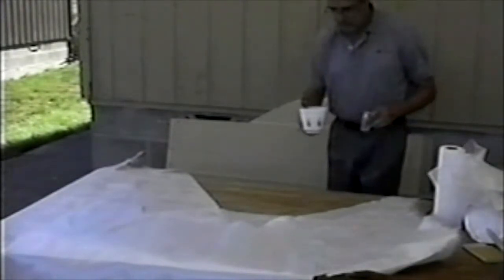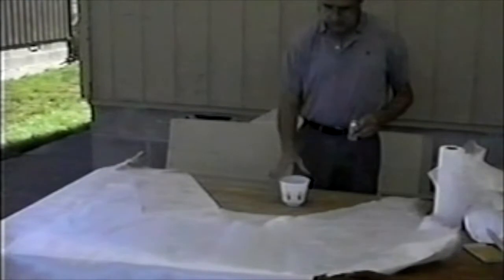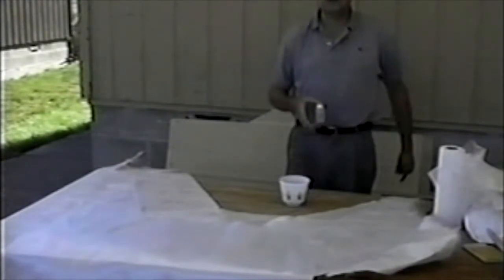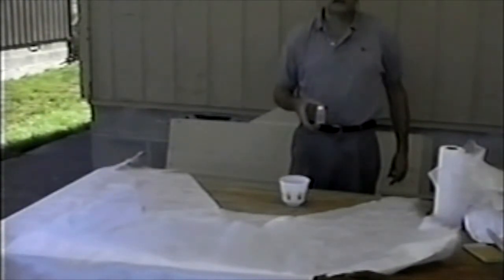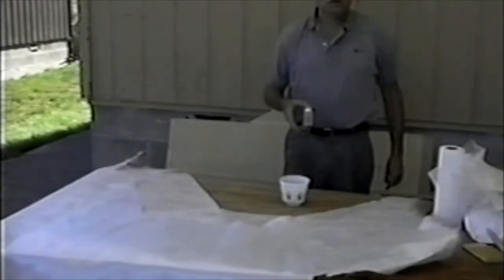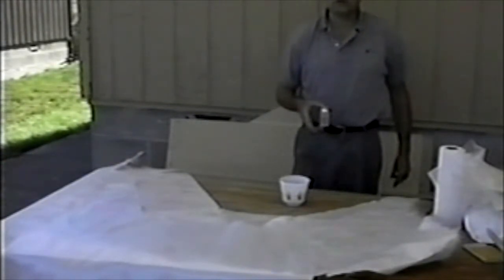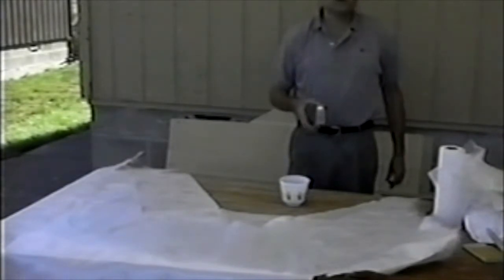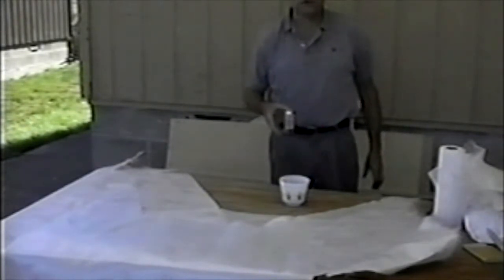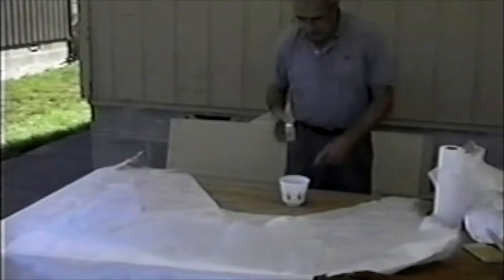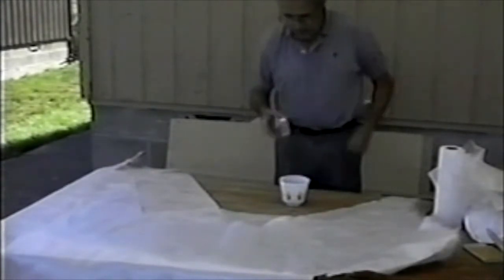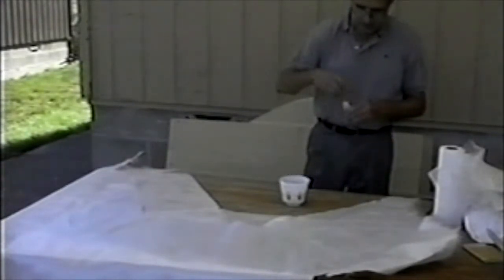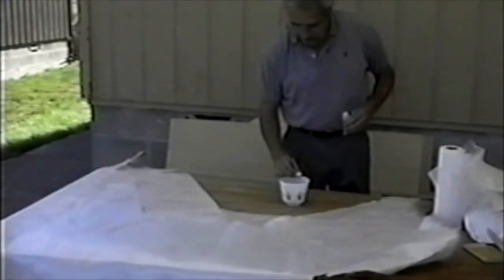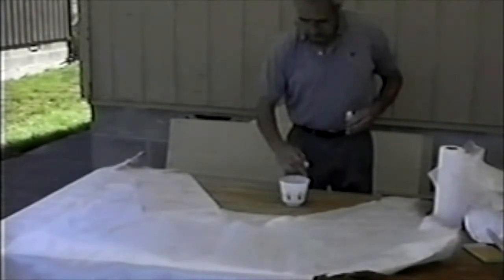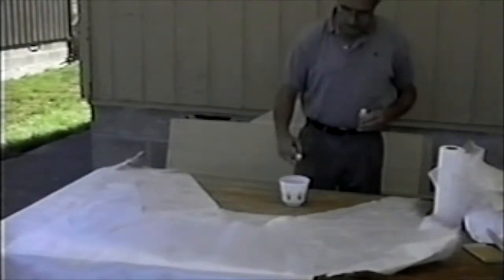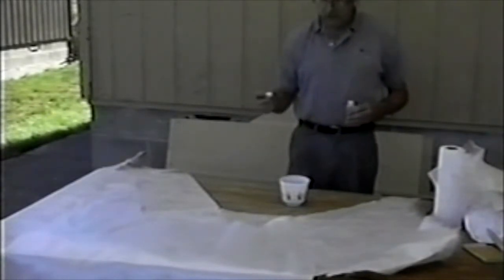To catalyze the resin, I look at the size of the resin container. I know I want between 1 and 2% catalyst for the correct setup of the resin. The more catalyst, the faster it sets up. The less catalyst, the slower it sets up. I look at the diameter of the liquid on the top, and I'm going to use the cap as a measuring device. It looks like the diameter of the resin in the can is about 5 times what the cap is.